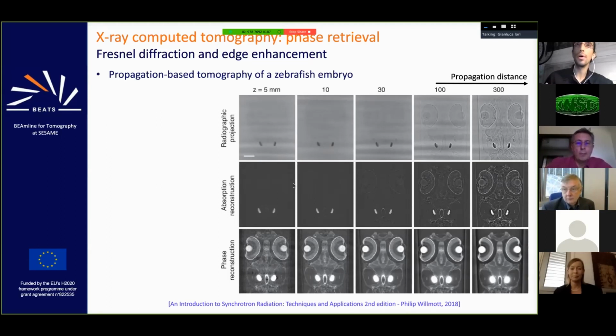So soft tissues with very low differences in electron densities, which we cannot see if we operate a normal radiographic projection or absorption contrast. And what you see is that increasing the propagation distance, the edges become visible because we go towards a Fresnel diffraction regime. And with the phase retrieval, phase reconstruction, which was introduced at the beginning of this century, we can actually reconstruct quantitatively the electron densities through these soft tissues.